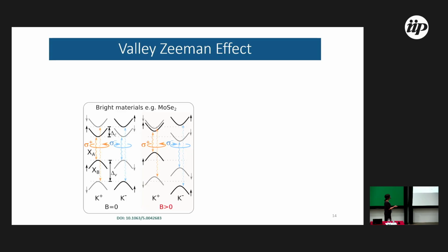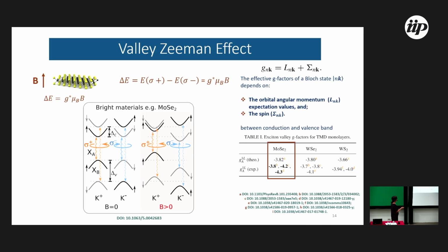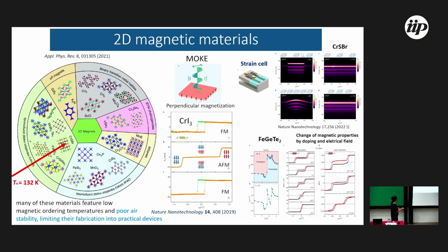So what happens when you apply a perpendicular magnetic field? I mentioned that the valleys are degenerate. You break the valley degeneracy, which means that the gap at B equals 0 is the same, but when you apply a perpendicular magnetic field, the gap from one valley and the other valley are different. And so you can measure, as you can measure circularly polarized photoluminescence, sigma plus and sigma minus.